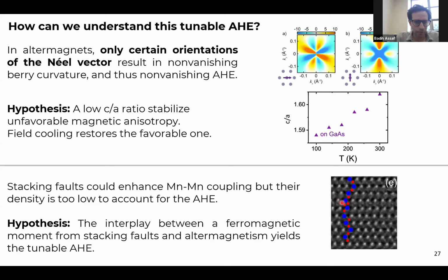As a result, there's an interplay between the local moments that these stacking faults generate and altermagnetism to tune the anomalous Hall effect. And on one hand, having it vanish without field cooling, and then on the other hand, allowing field cooling to train some of these local moments that are localized around this defect to spontaneously organize and generate an anomalous Hall effect.